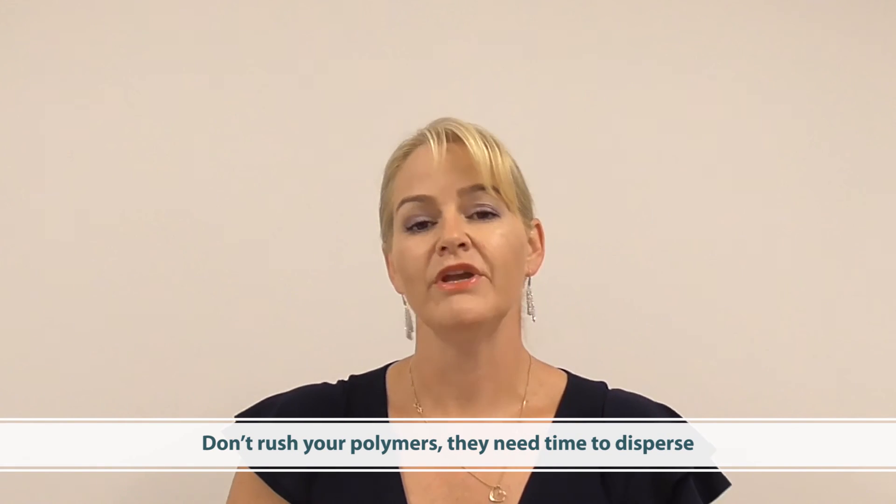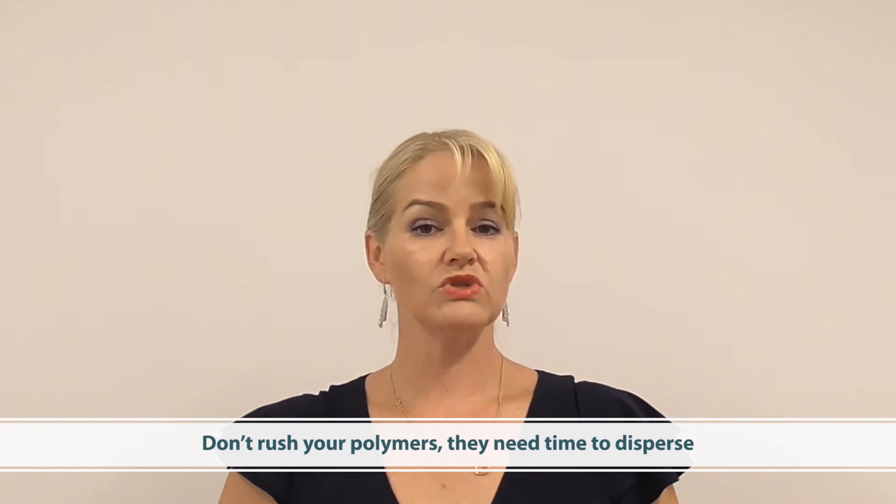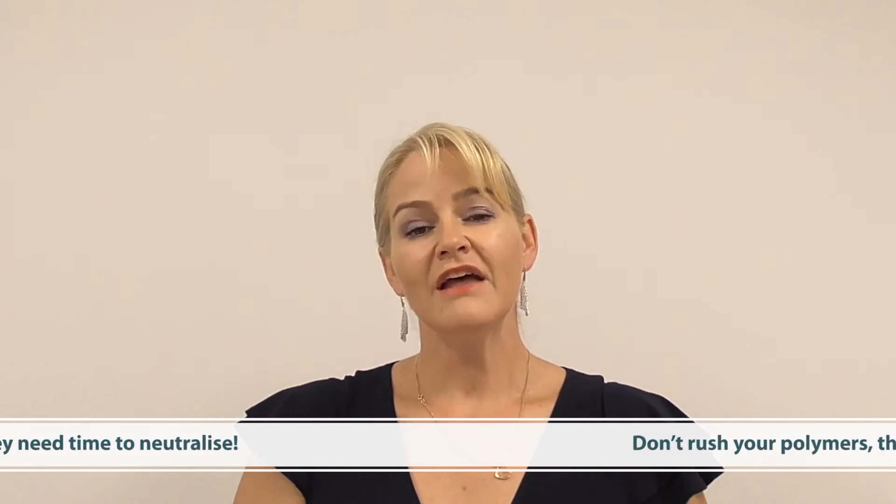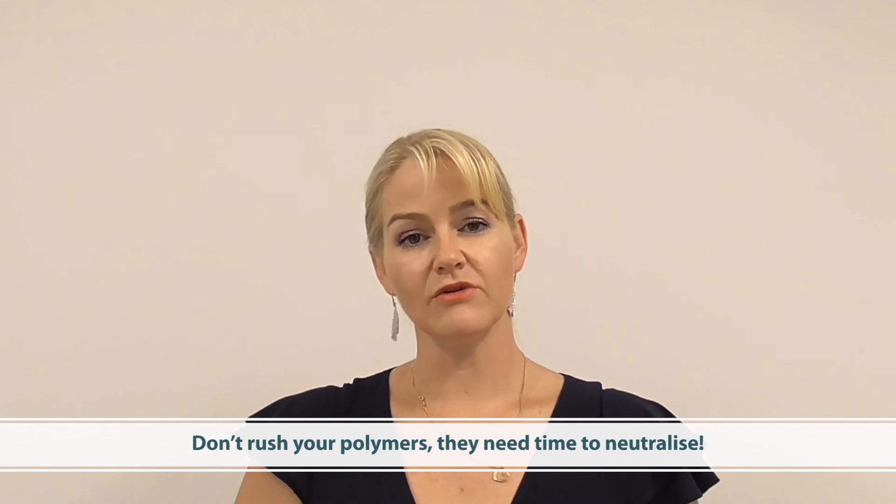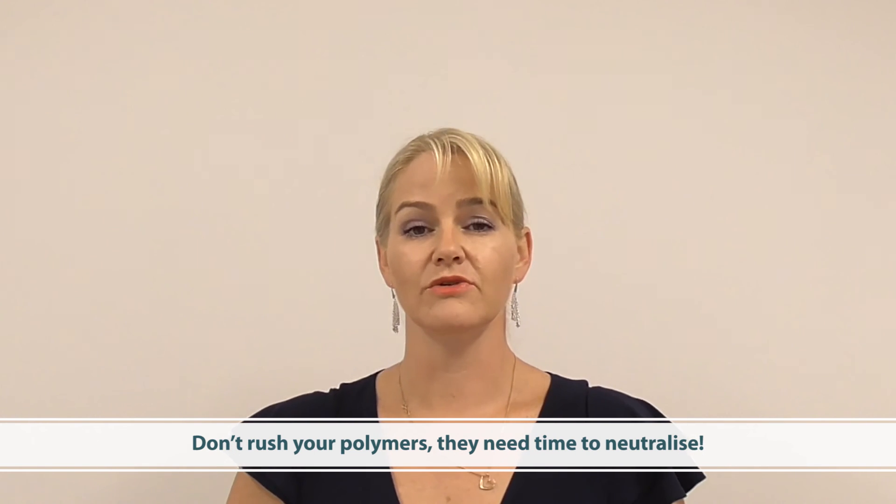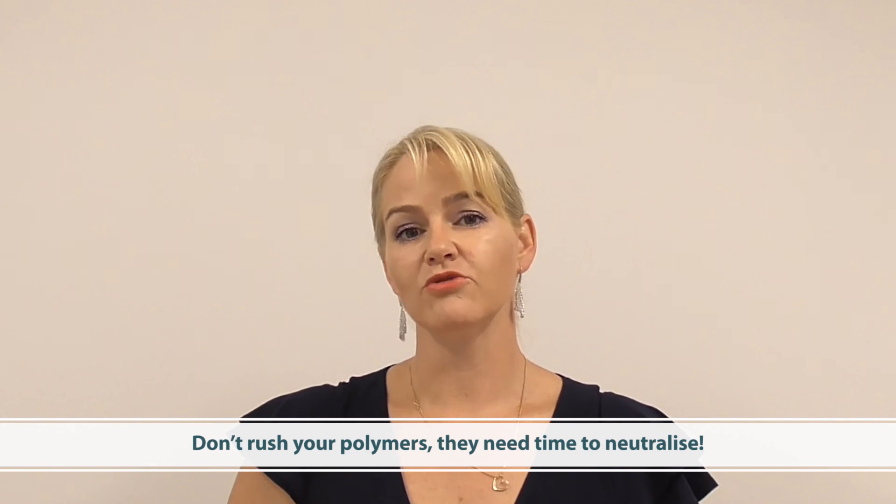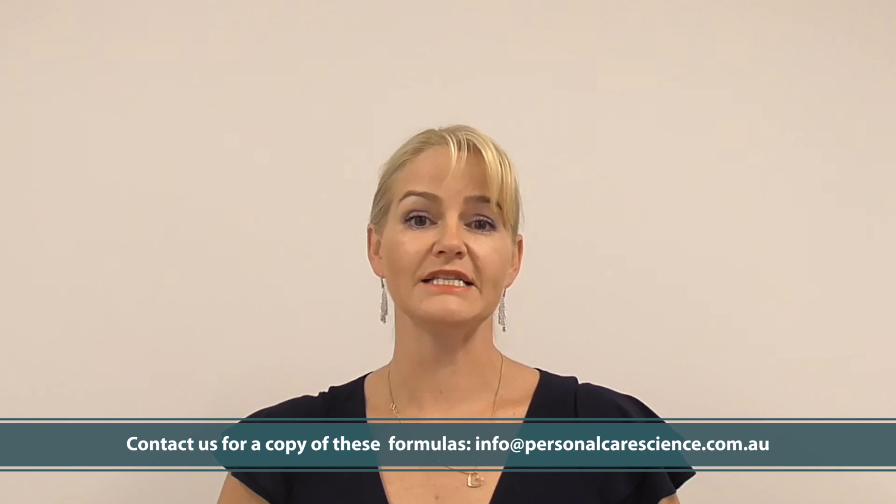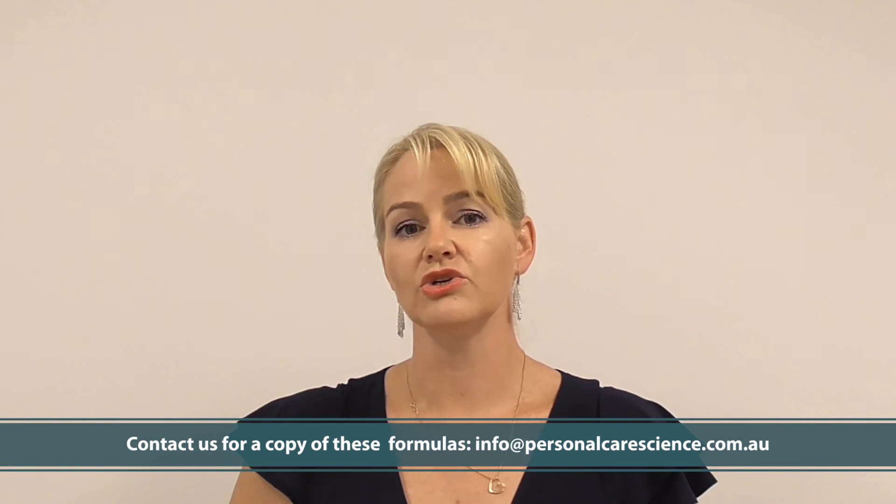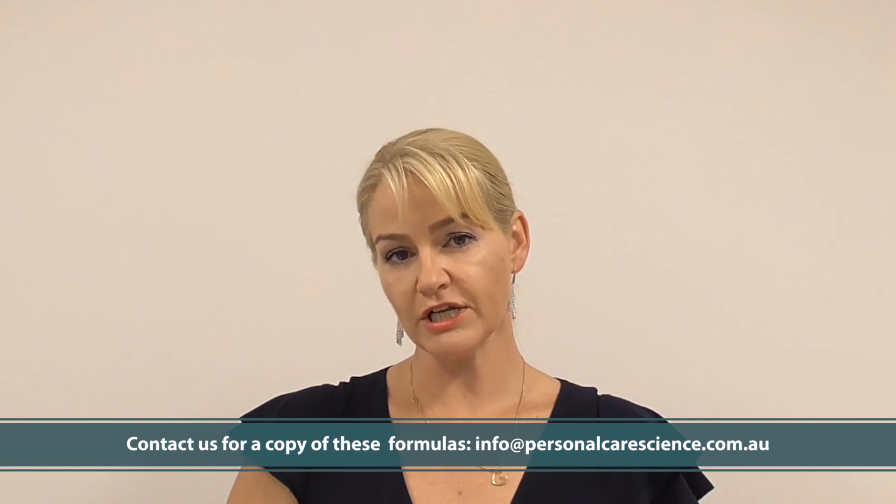Now just a word of caution. You can't rush a polymer at the early stages, as you saw me do I have thoroughly wetted them before I neutralized them. They still do need thorough stirring after the neutralizing step but it must be low shear at this point. So you'll need to make sure you've got some paddle blades or side sweeper blades to ensure the product gets homogeneously mixed and turned over to ensure it's fully neutralized to get full viscosity and stabilizing benefits.